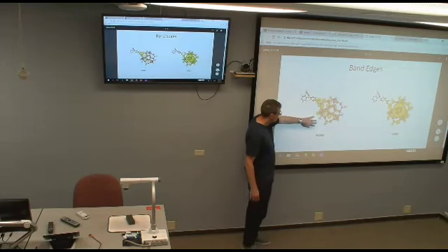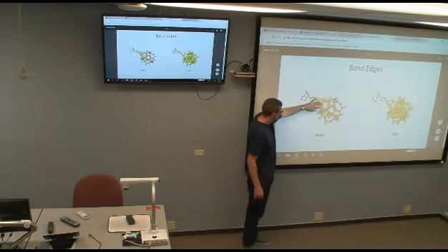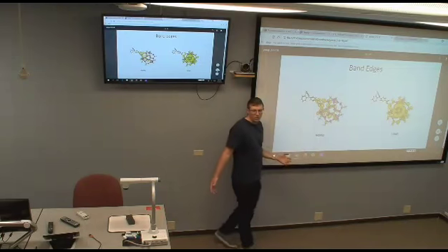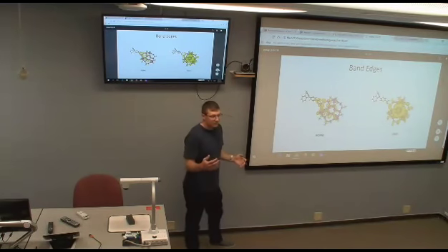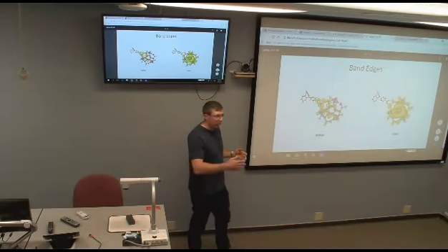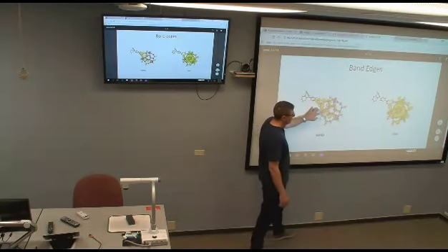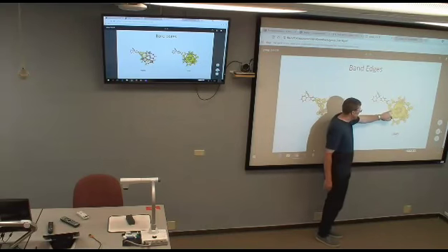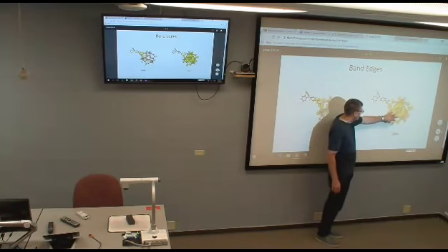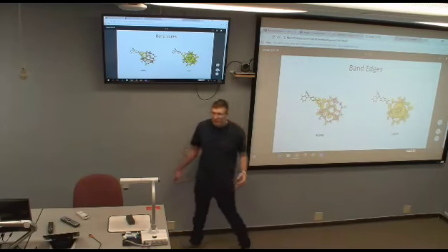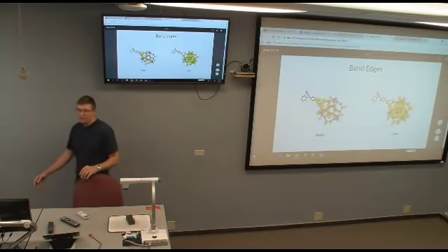And so you can see on the HOMO there's going to be orbital distribution coming up into this carboxylic group and slightly onto some of the rest of the organic piece of the dye, which is what we want. We want this type of hole relaxation to migrate onto the organic pieces so it can be pulled off of the quantum dot, while the LUMO is shown primarily to be localized on the quantum dot itself, allowing for some type of charge separation of the exciton after it's generated.